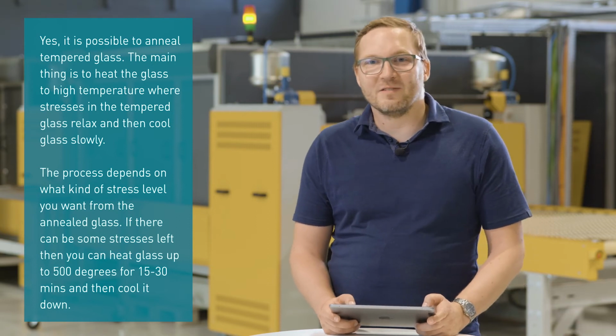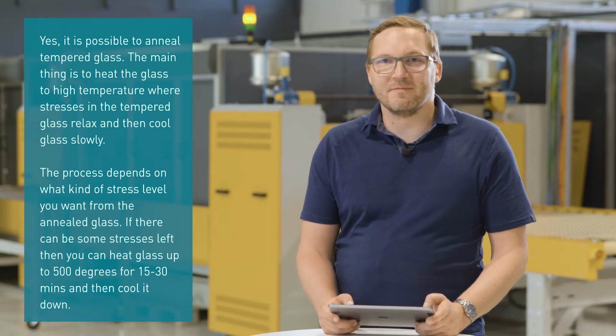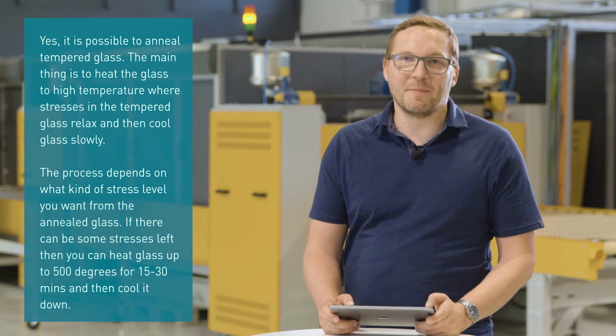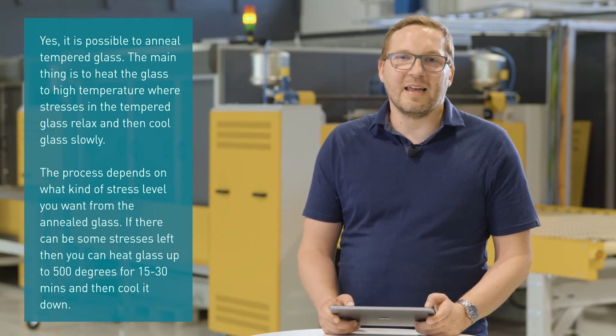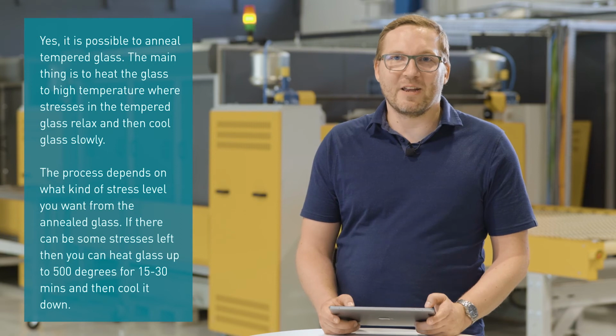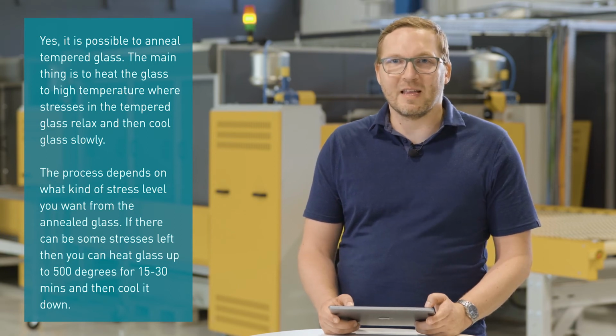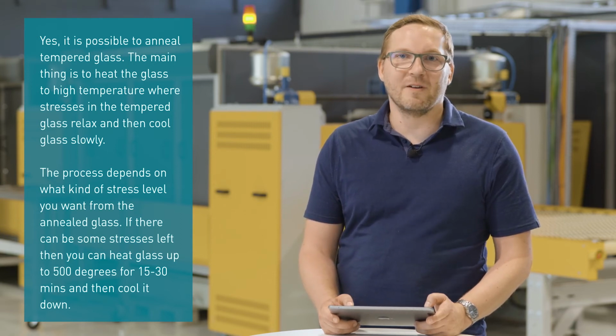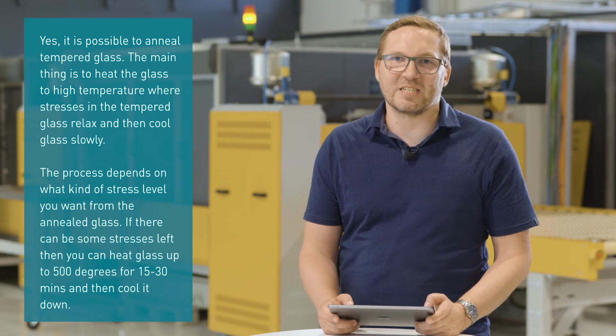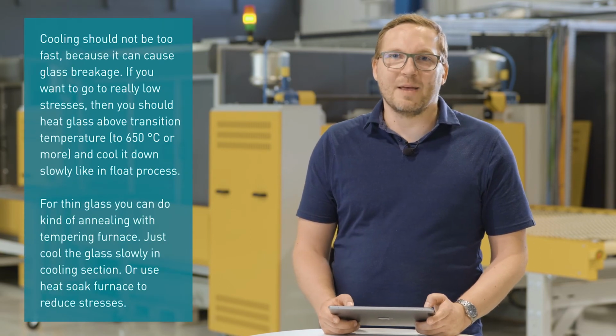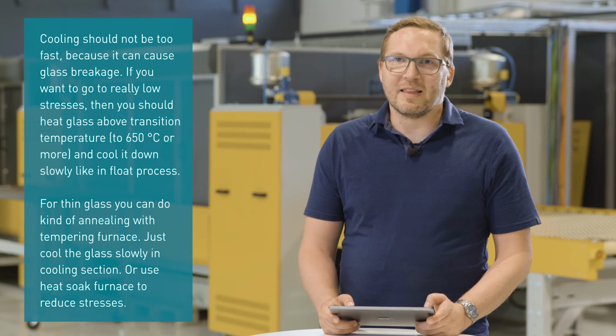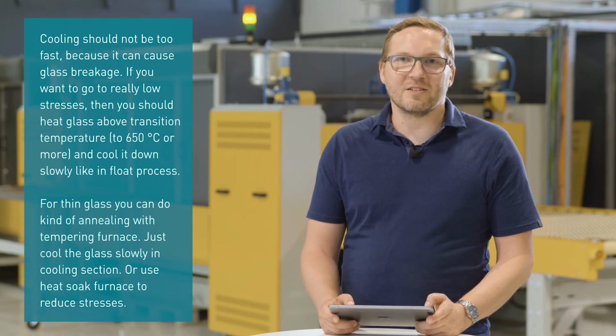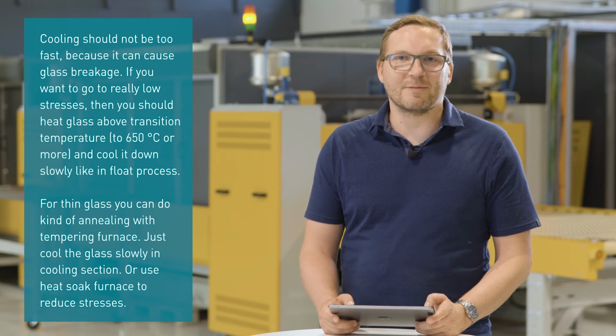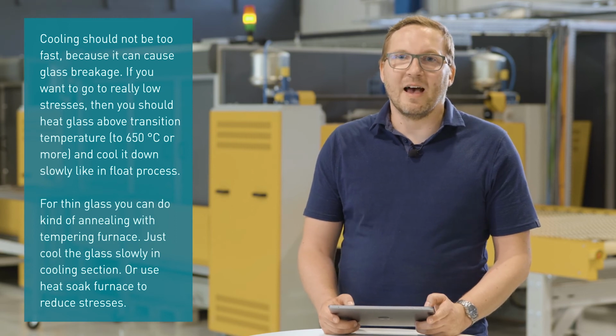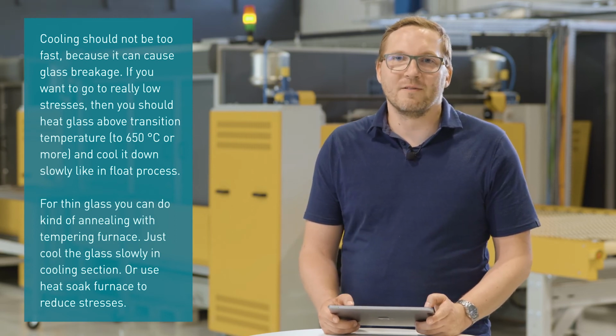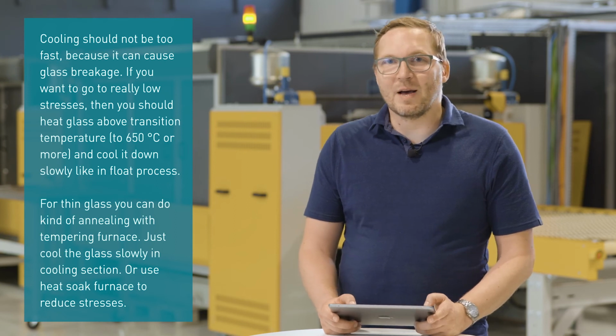So if you want to decrease the stress level from 80 megapascal surface stress to maybe 30-40, then heating glass up to 500 degrees for 10 minutes, half an hour, that might be enough to anneal glass to that stress level. But if you want to get the same level as float glass, then you have to heat the glass to the highest temperature level, like 650-700 degrees, and then cool down really slowly, just a couple degrees per second.